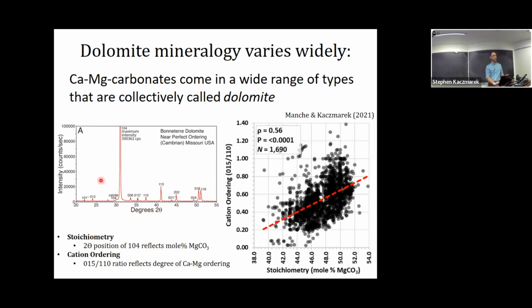There's an inverse relationship between the 2 theta angle and the D spacing, the interplanar spacing within the mineral. So larger calcium ions mean a smaller 2 theta angle, and it pushes the whole pattern to the left. More magnesium pushes the pattern to the right. We also measure the ratio of this 015 ordering peak to another peak in the pattern, the 110, which is not an ordering peak. 110 is there whether it's calcite or dolomite. As this ratio increases towards 1, the inference is that we're getting more and more ordering.